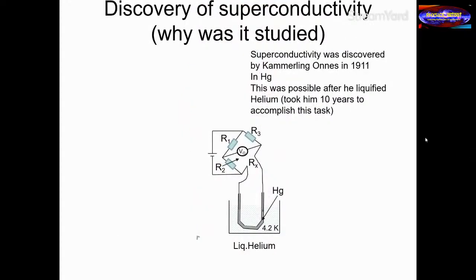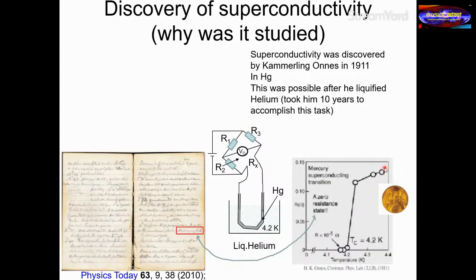Okay, so what Kamerlingh Onnes did was, now if you take pure mercury, you make mercury very pure, what happens to mercury's resistance if you start cooling it down? So he took a glass U-tube, in which he put mercury, and there are these two arms of this mercury. The two ends of this mercury are actually connected to a Wheatstone bridge, which you would have studied, so that you can measure the resistance of mercury. And he started cooling down the temperature with his liquid helium. And when he cooled down this mercury, then abruptly at 4.2 Kelvin, there was a huge drop in resistance.